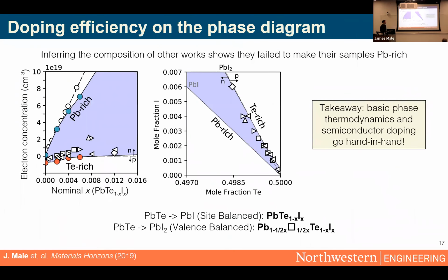The conclusion here about repeatability is basically that all of these researchers simply failed to make their samples all the way lead rich, and that's what gave them bad doping efficiency. And it's really not their fault, because this phase width is so small that you can't even measure it by XRD or SEM, at least in most cases. So really what they need to do is just think about phase equilibrium and ensure their sample is ever so slightly lead rich. A simple conclusion for just lead telluride, but what it means is now we